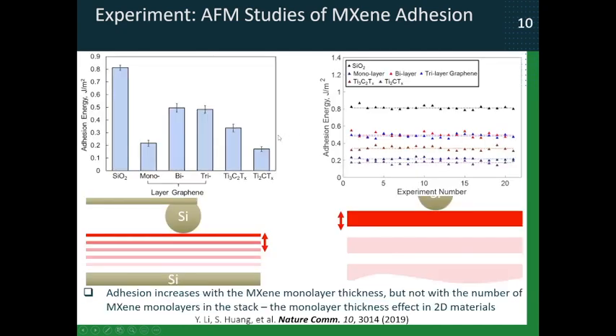Now, when we started to look deeper into this, it turns out that for materials like graphene, we observe this dependence of adhesive force on the number of monolayers in the stack. And when we go from monolayer graphene to bilayer graphene, the adhesion increases dramatically. Then we go to 3-layer or 4-layer or 5-layer graphene, and adhesion force doesn't change much. So for graphene, the behavior is this: initially, the adhesion is very sensitive to the number of layers in the stack, right, going from mono to bi. But then this effect disappears. Starting from 3-layer and more layers, the adhesion force is constant.